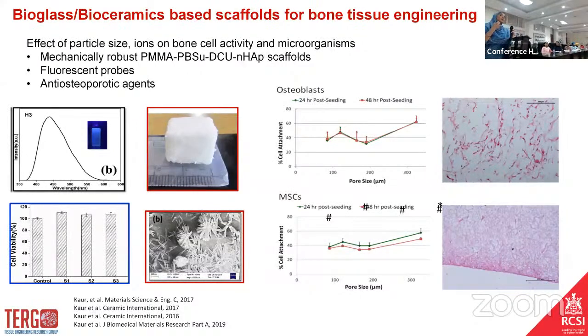And then I prepared mechanically robust PMMA, PBSu, DCU is a polyester, and hydroxyapatite scaffolds, then prepared fluorescent probes, because when we implant our material in the body, we want to track where it is at its current position. So we need some fluorescent ligands on the surface of the biomaterials. Then I prepared anti-osteoporotic agents.